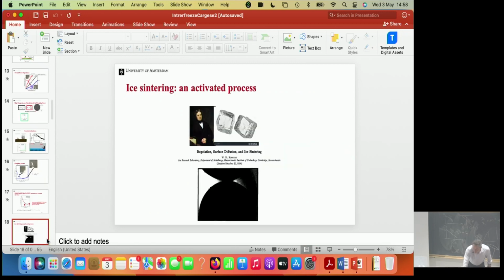And so the question is, of course, what is the activated process? And so I dove into the literature, and there's lots and lots of things already known about ice. And there's an MIT professor of ceramics who was very interested in sintering, because making a ceramic material is sintering two solid materials without any liquid being present into a continuous film. And that actually looks like ice sintering, and he must have had the same idea, because he redid the Faraday experiment, who had these two ice cubes that he brought together.